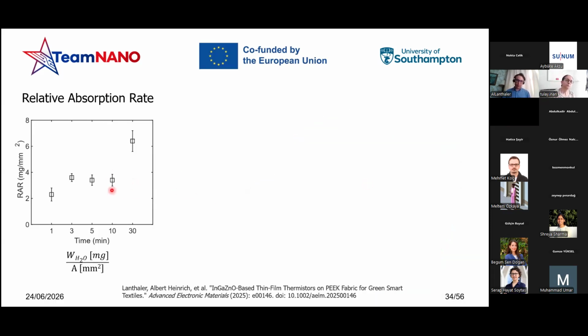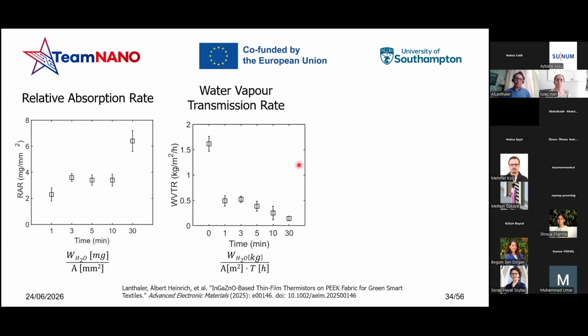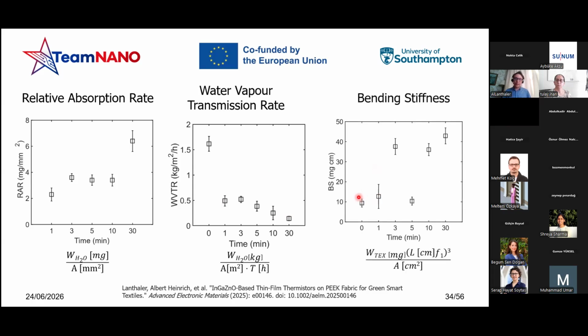How to do that? Well, first things first, we wanted to understand the relative absorption rate of the fabric itself, aiming for no waste of PVA on top of the fabric itself, dipping the PEEK PVA fabric into the PVA solution for different coating times: 1, 3, 5, 10, and 30 minutes. Then after that, we wanted to investigate again the water vapor transmission rate compared to the pristine fabric and see how the coating layer affects the breathability of the fabric itself. And last but not least, understand the bending stiffness of the fabric, and how the coating layer affects it.